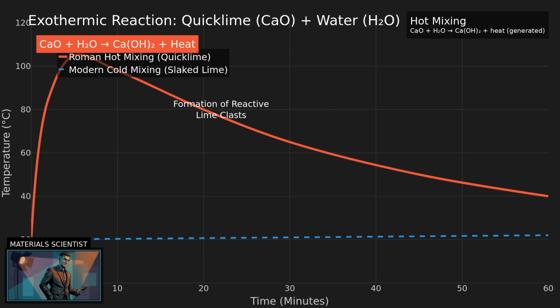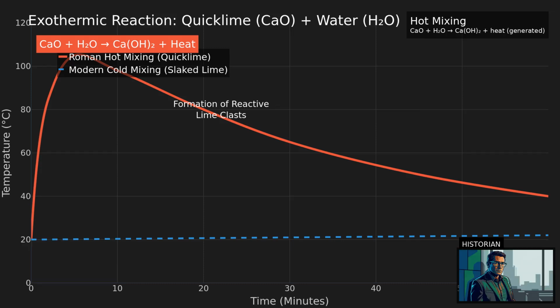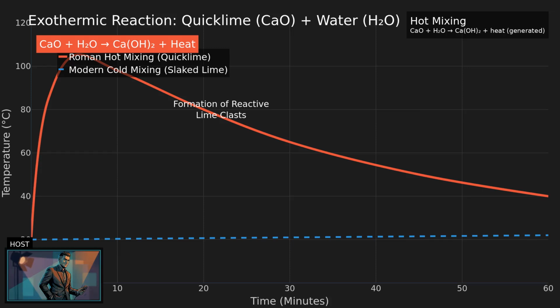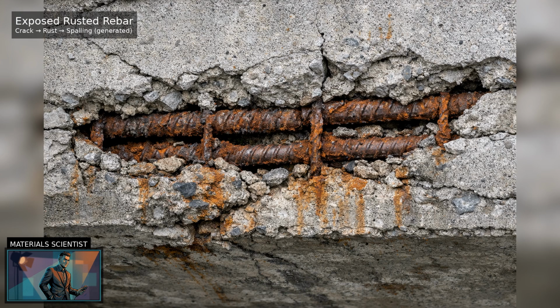When tiny cracks form and water seeps in, the clasts can dissolve a bit. That calcium-rich solution moves into the crack and, over time, minerals, often calcium carbonate, reform and help seal it. In lab tests with Roman-inspired mixes, researchers have watched cracks stop leaking within weeks, sometimes in about 2 weeks. That is incredible. So the water that usually destroys modern concrete actually saves Roman concrete. In small cracks, it can.